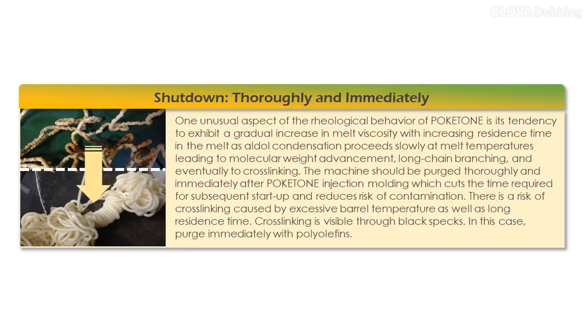There is a risk of cross-linking caused by excessive barrel temperature, as well as long residence time. Cross-linking is visible through black specks. In this case, purge immediately with polyolefins.